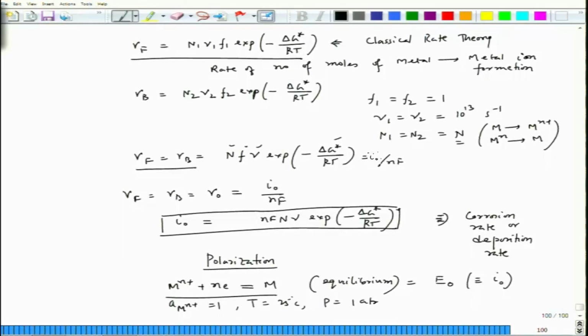be E 0. That means activity of M n plus equal to 1, temperature equal to 25 degrees Celsius, and pressure equal to 1 atmosphere. Then it becomes E 0. So, if this equilibrium is disturbed, and how can we disturb? This is I C, this is I A with a negative sign. Let us say I supply a little extra negative current. This negative means we are supplying a little extra cathodic current, which is opposite to the anodic current.